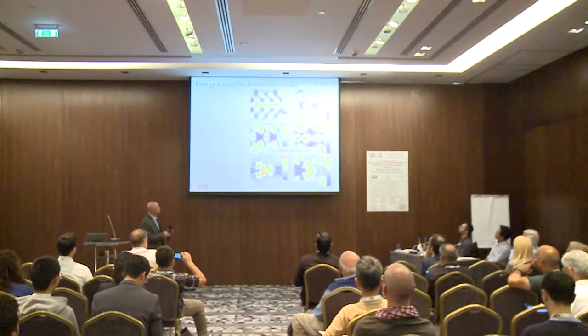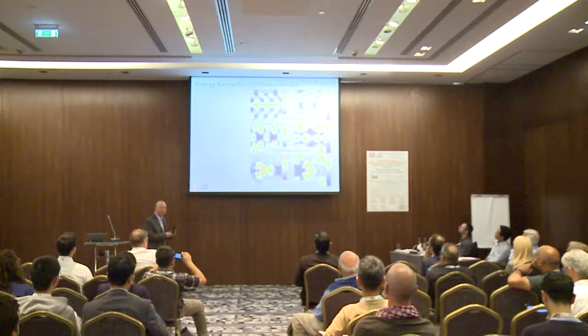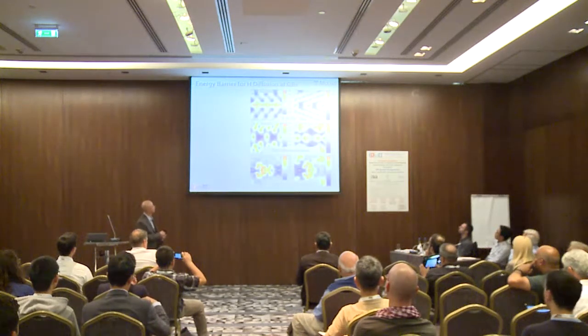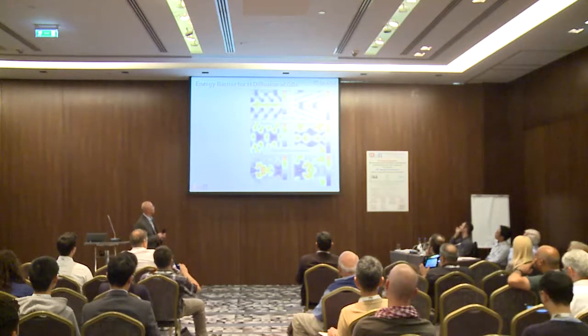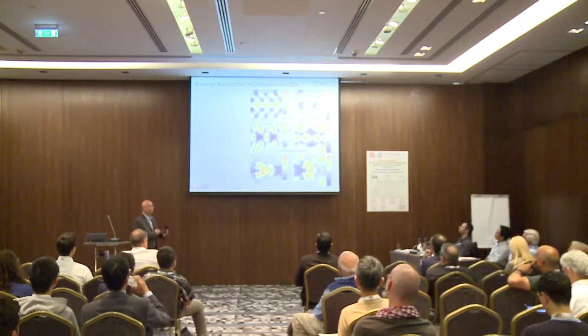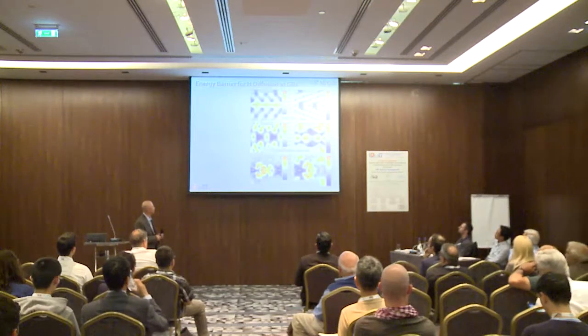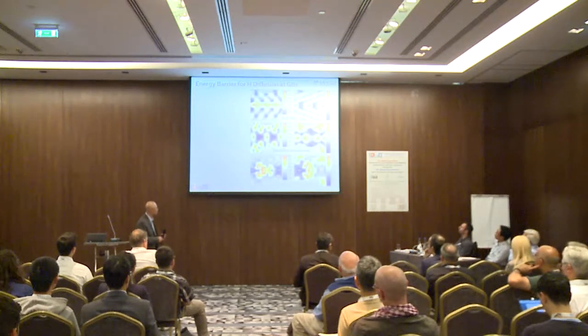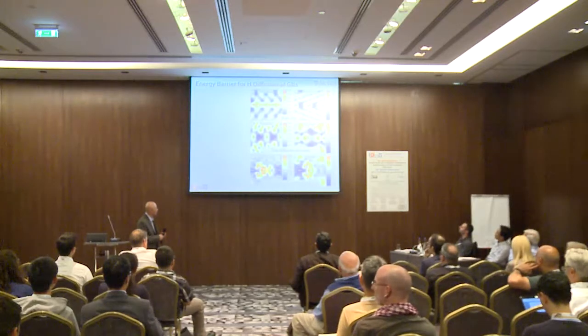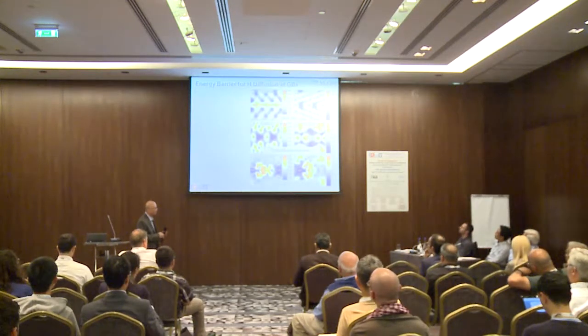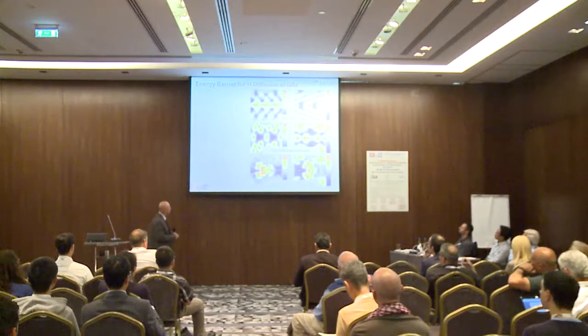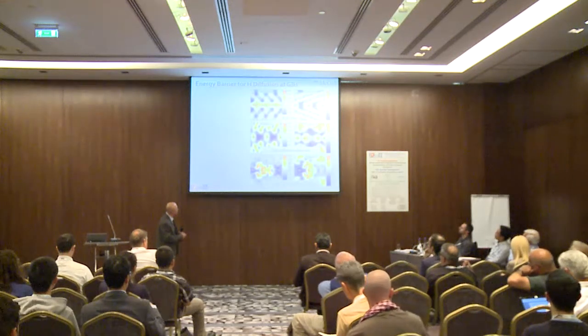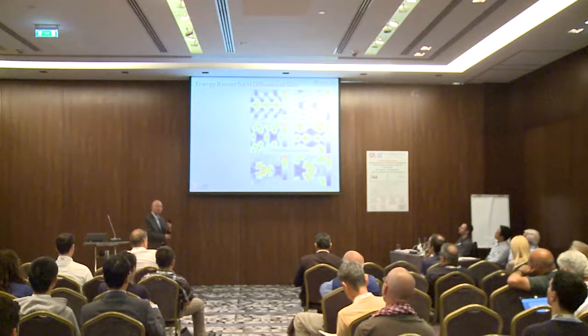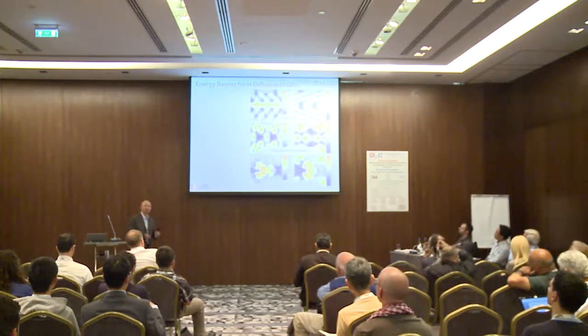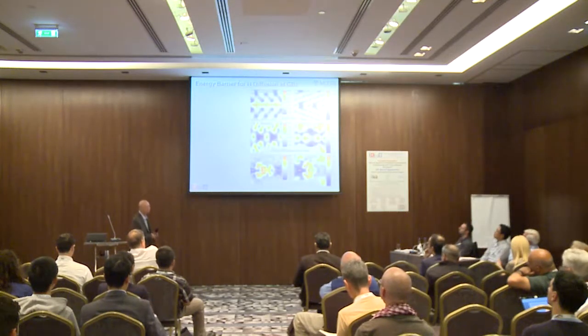Okay, so just from those contour maps, we get an idea that for these different sets of grain boundaries, the first set could have bulk-like diffusivity, the second set could have fast diffusion, while the third one can have trapping, where hydrogen gets in and cannot escape. By the way, although it isn't shown here, those high barrier regions correspond to low energy states for hydrogen. So hydrogen actually prefers to go there, and once it goes there, it cannot escape, or it's difficult.